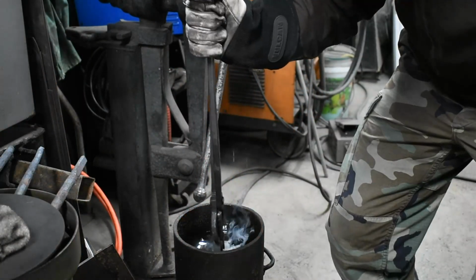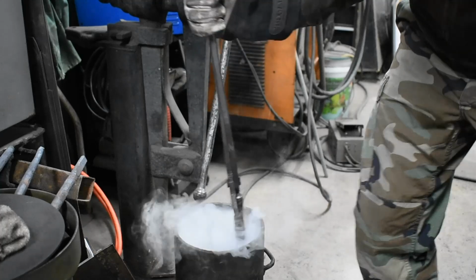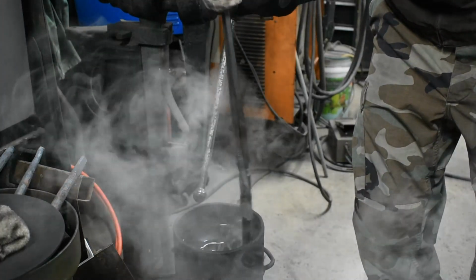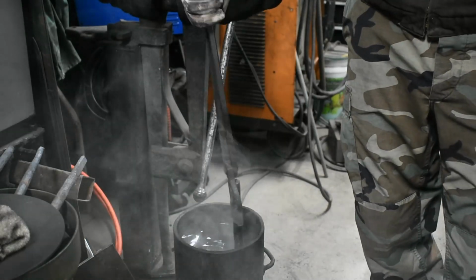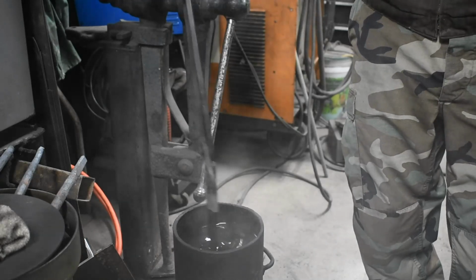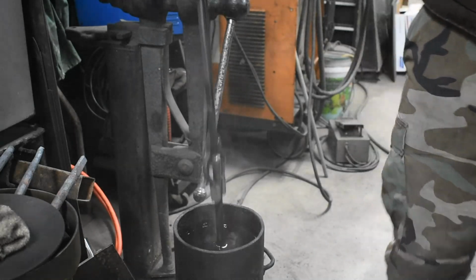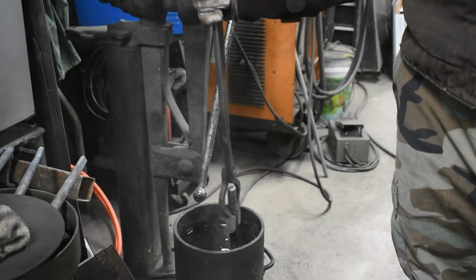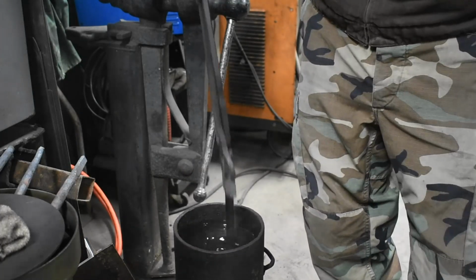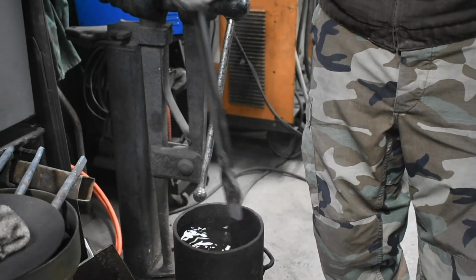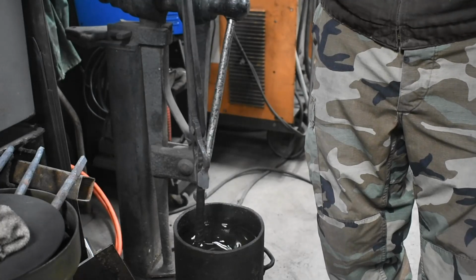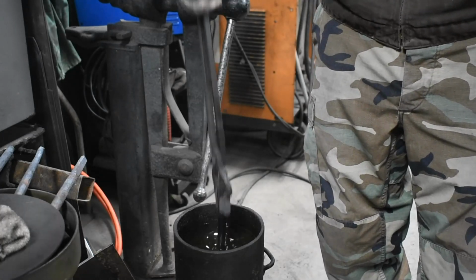So right now I'm just quenching a big preheated piece of steel into my Parks 50 to preheat it to get a better quench, because it's like 40 to 50 degrees in the shop, even with the wood stove going for a little while already. Even in the summer, I usually like to preheat my Parks because you just get a better quench out of it. Lots of stirring.